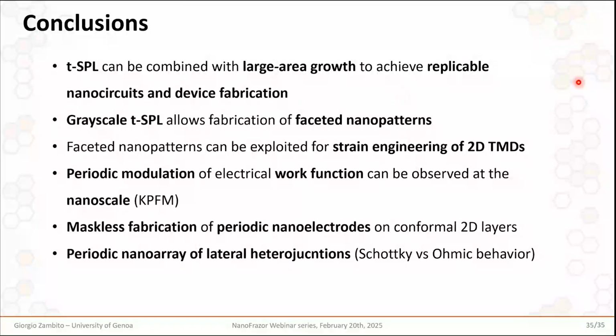So this is the end of my presentation, and I hope that I showed you some interesting results dealing with NanoFrazor lithography. First, how we combine thermal scanning probe lithography with larger-scale approaches for growing 2D materials to achieve replicable nanogeometries, nanocircuits made of MoS2. And also that grayscale thermal scanning probe lithography can be a very useful tool for devising faceted nanopatterns that have the twofold advantage of inducing strain with appropriate transfer approaches, but also of confining gold on top of two-dimensional strained materials in a very clean way. And that these can allow us to change the nature of the semiconductor-metal junction that we create.